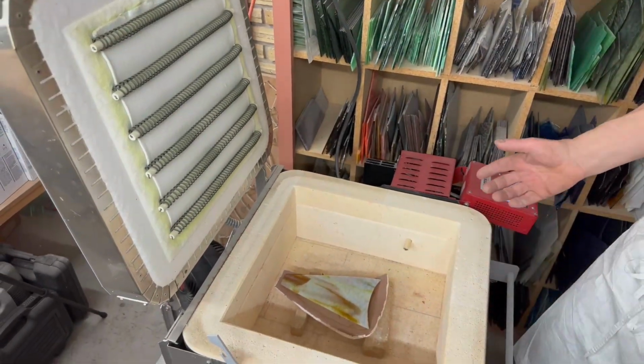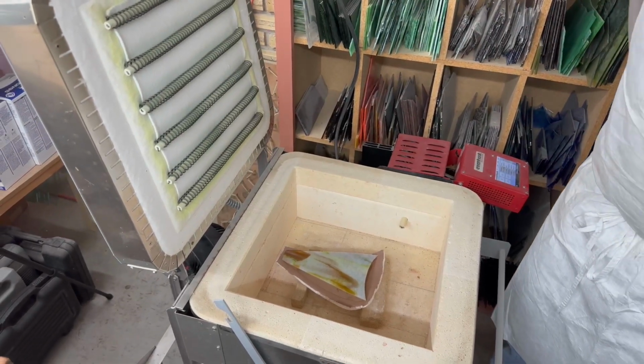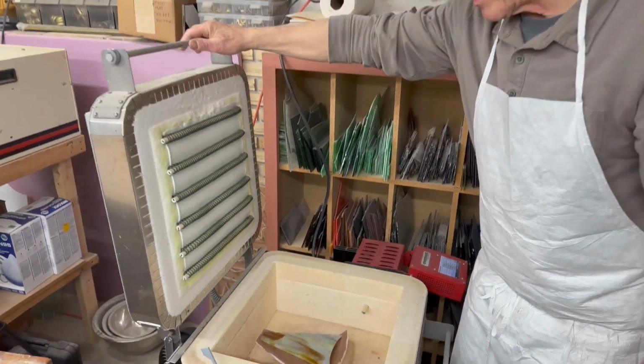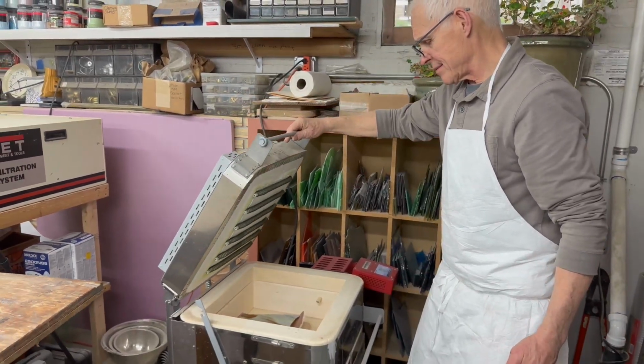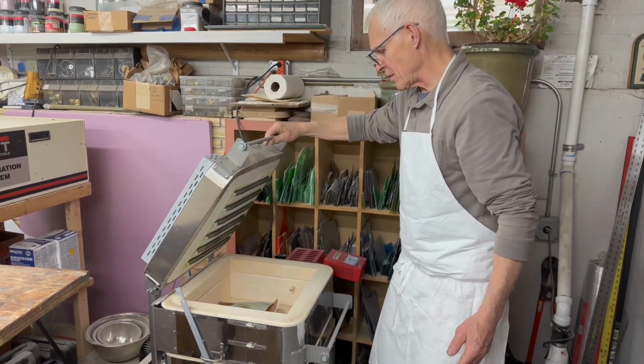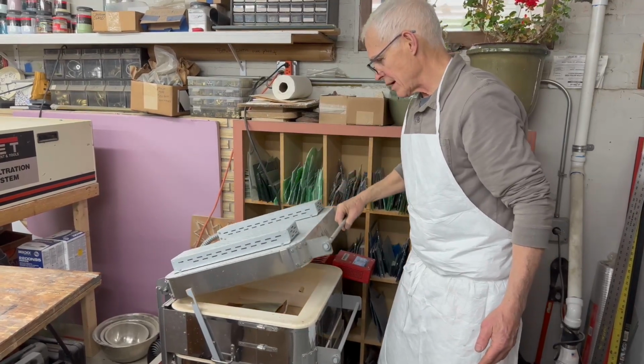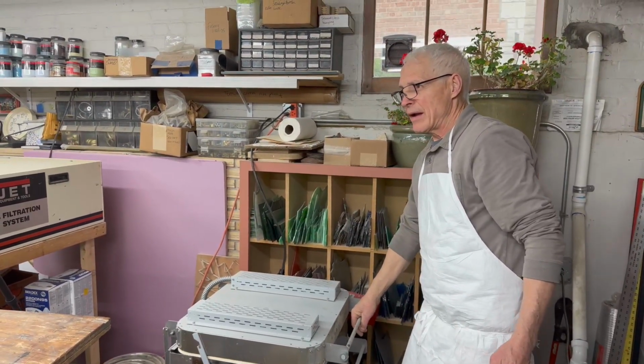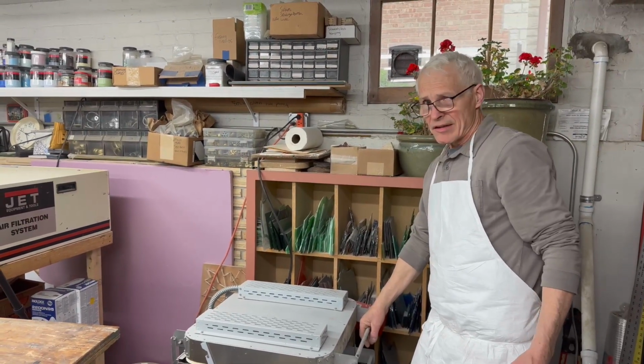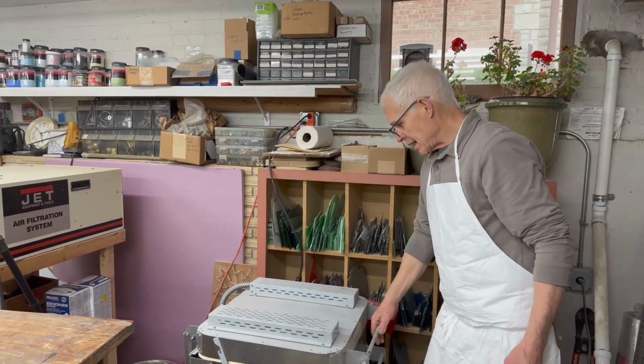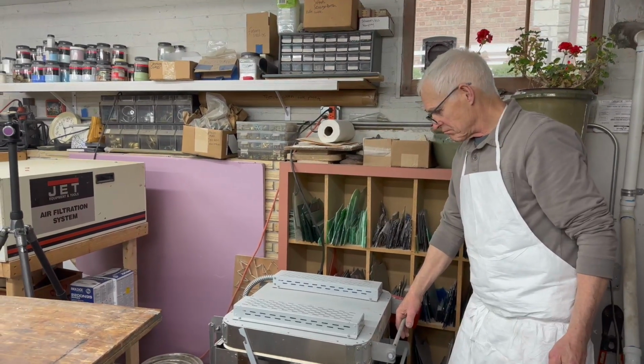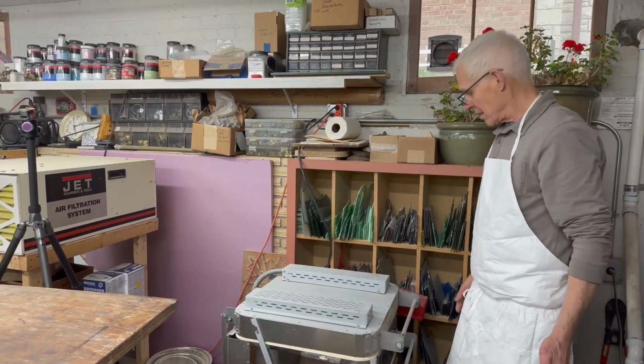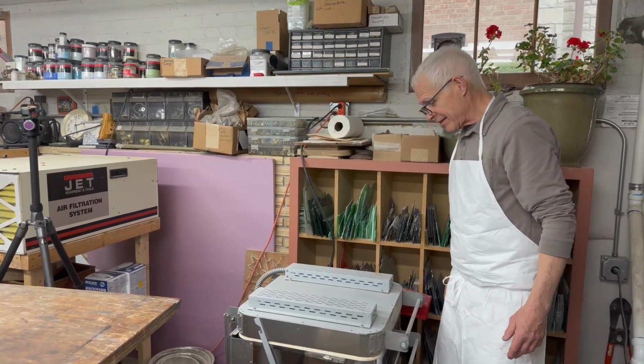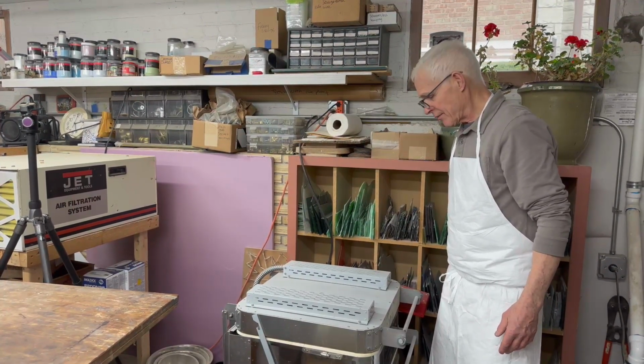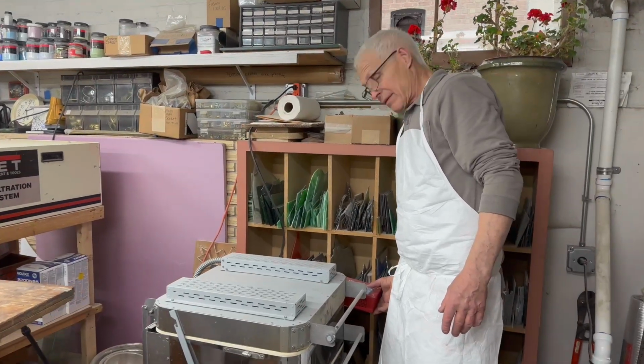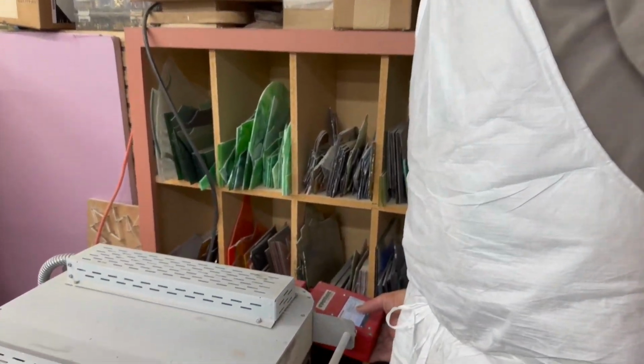Okay, so there it is. We'll probably put this at the similar firing of 1125 Fahrenheit with a ramping up time of 500 degrees per hour, and I think it's on like a 10-minute soak, and at that point it shuts itself down and cools real slowly. So we'll check it out after it's done.